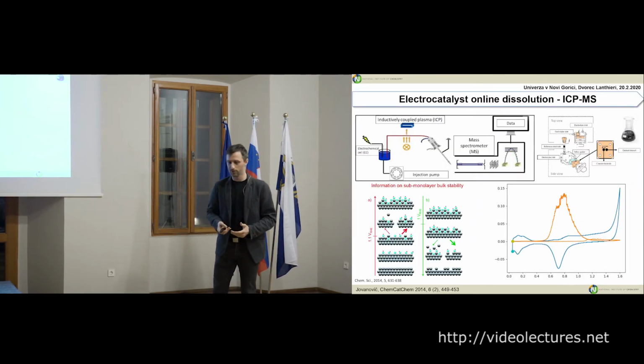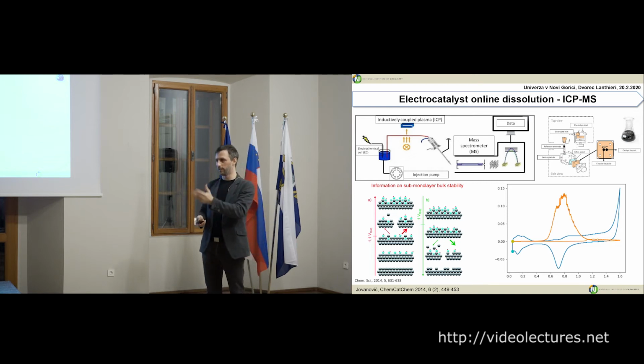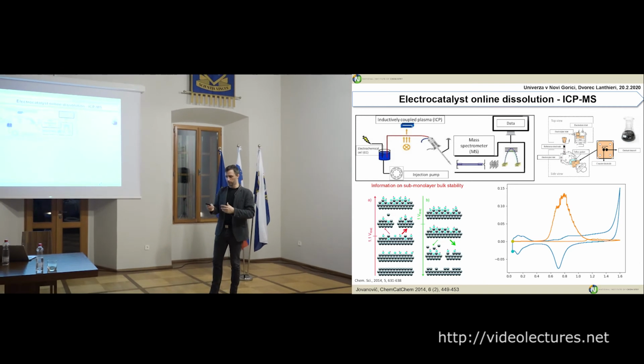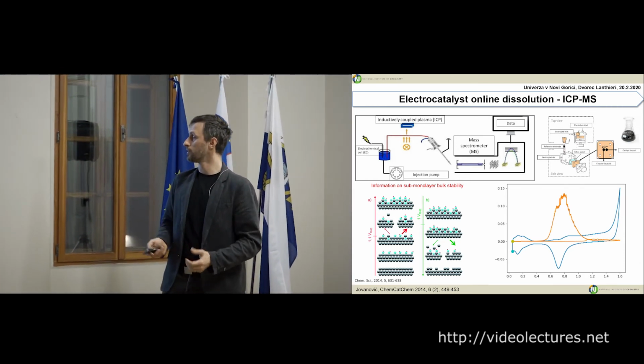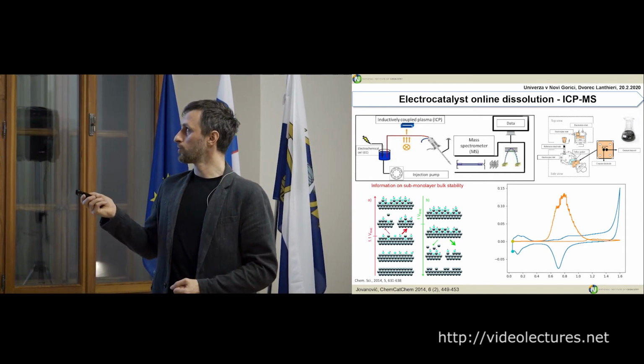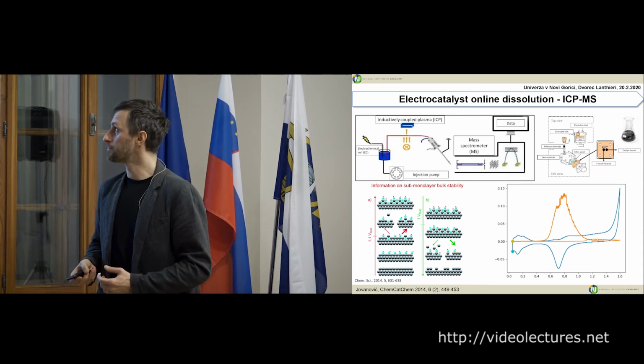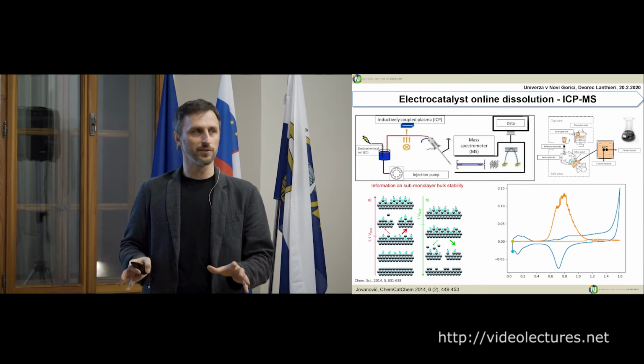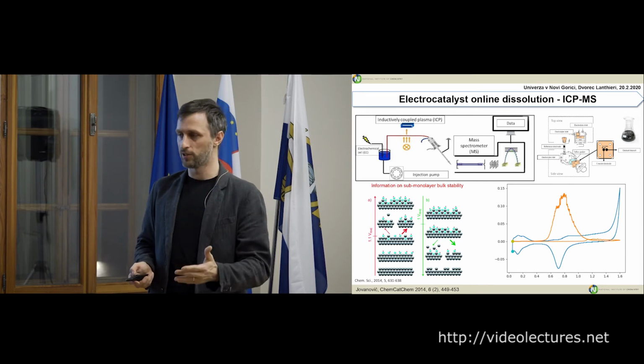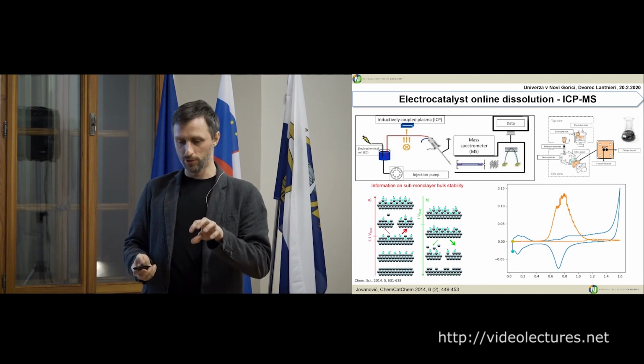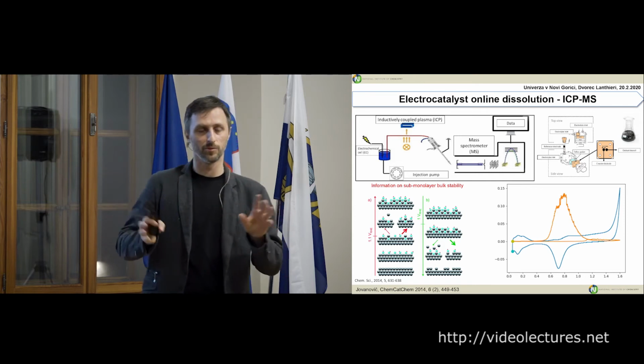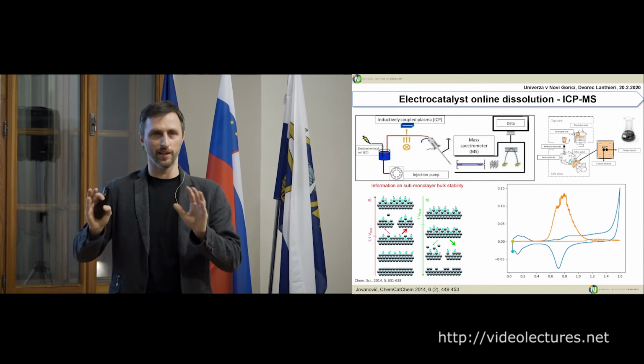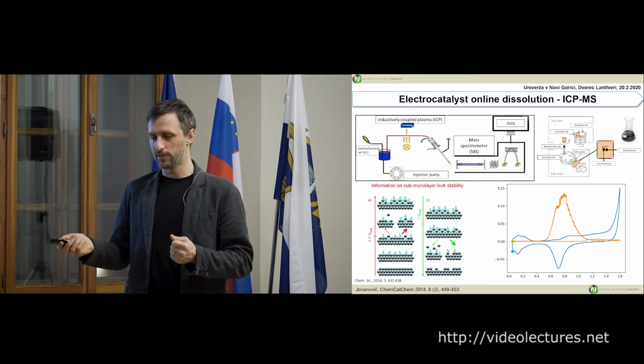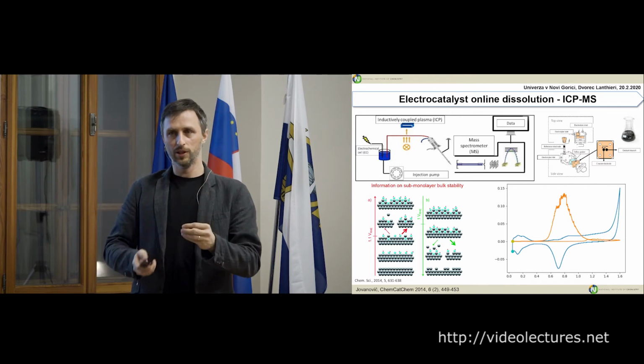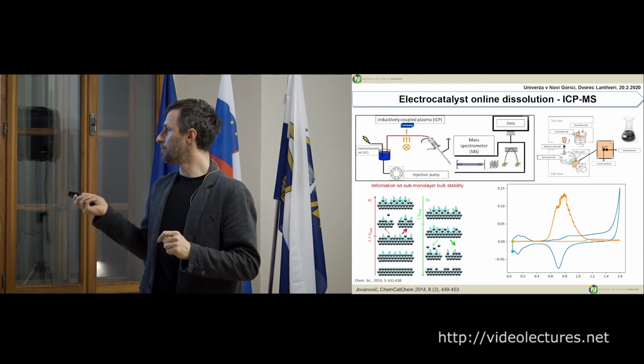Now there is one technique I also need to mention. It was developed, of course, through an idea that we saw somewhere else, but it was developed with a new cell and a new kind of coupling. So what you do, you use ICP-MS, or inductively coupled plasma coupled to MS. This is a very sensitive technique. And in this case, we want to measure online dissolution. So you have your electrochemical cell, which is kind of complex here, but don't worry. You pump the electrolyte into the ICP-MS directly. And because it's so sensitive, and because this electrochemical cell is small volume, you can actually track the online dissolution of platinum.